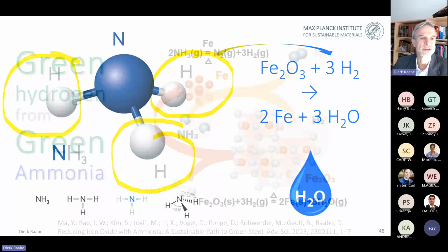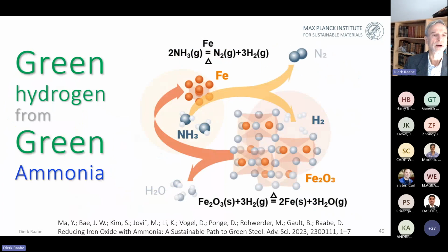And then you go through this autocatalytic reaction where the more iron is formed, the quicker the transformation of ammonia into nitrogen and hydrogen works, and you then use the hydrogen to reduce the iron. And you do all in the same reactor. The reason was that ammonia is much easier and at much lower cost to transport than hydrogen. As we all know, you only need something like minus 37 degrees centigrade to liquefy it. So it's much more cost efficient than doing that with hydrogen.